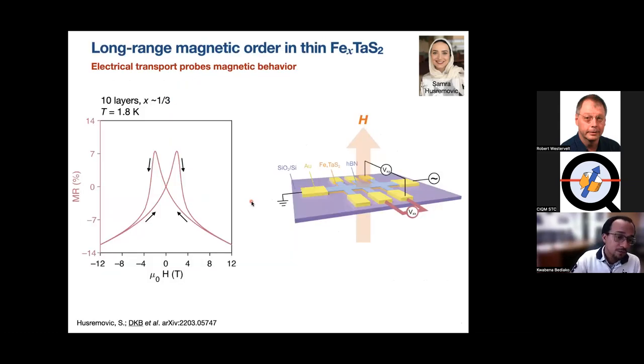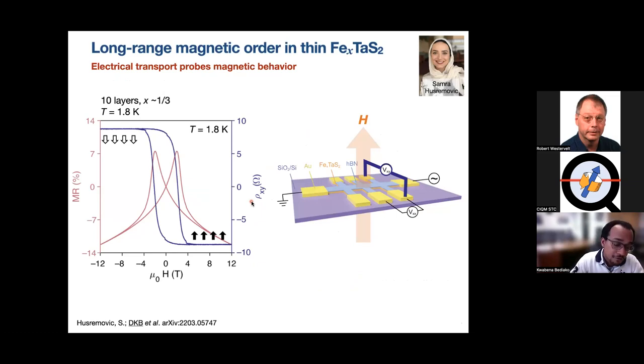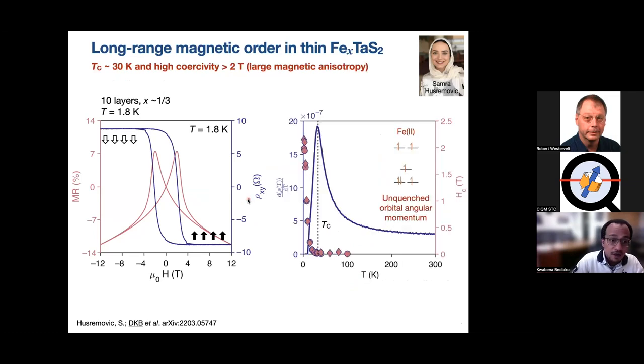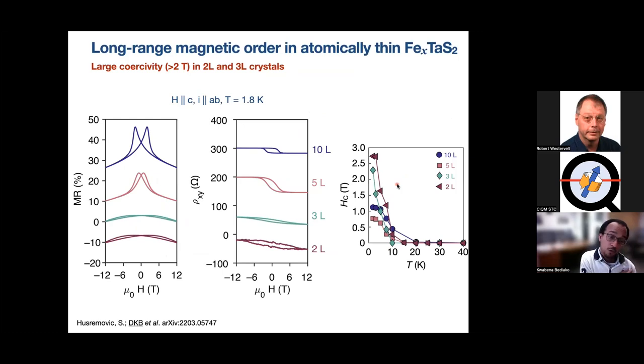And then the big question we had was, okay, what happens in these thin flakes when we cool them down and sweep the field? And sure enough, we see all the hallmarks of magnetic ordering, of ferromagnetic ordering. And impressively, these are extremely coercive materials. And that arises because you have this unquenched orbital momentum from the iron two that then produces coercivities that exceed two Tesla or so, making these some of the most coercive 2D magnets.